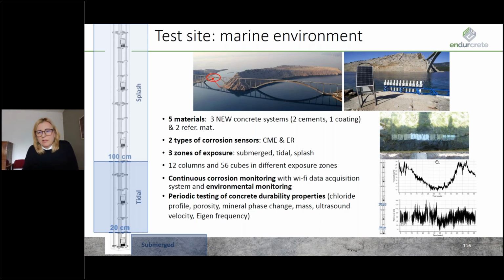Construction site. The 5 materials were used at this site, so there were 3 cements, both presented in the tunnel and the marine environment, so 2 EnDurCrete cements, and additionally 1 set of samples was coated with 1 polyurethane coating, and we had 2 reference cements as well used for a marine and the tunnel environment.